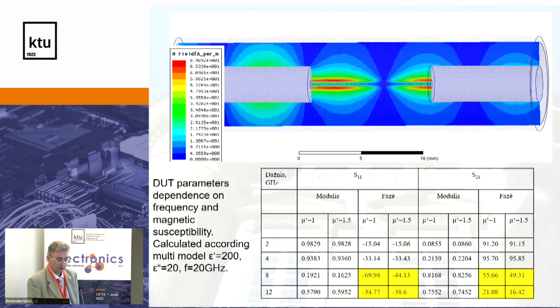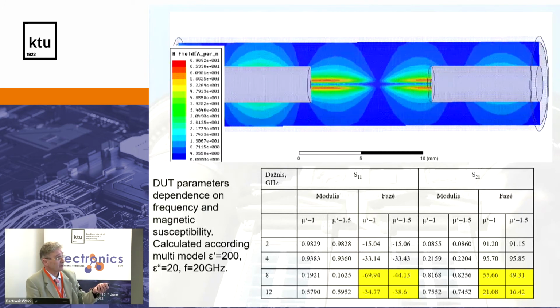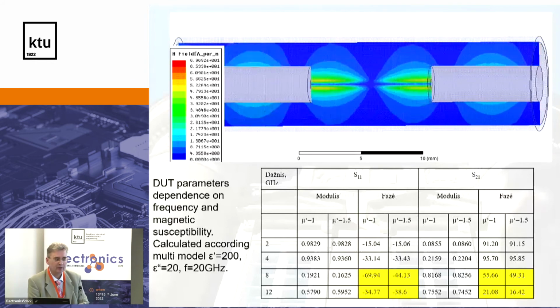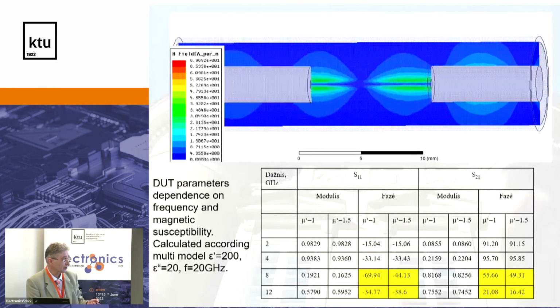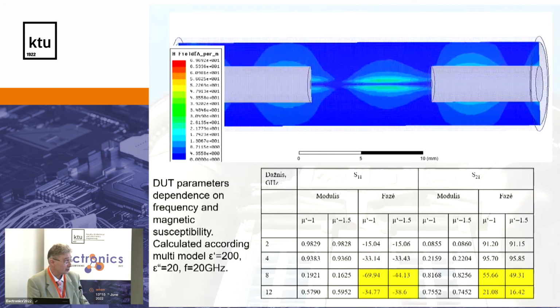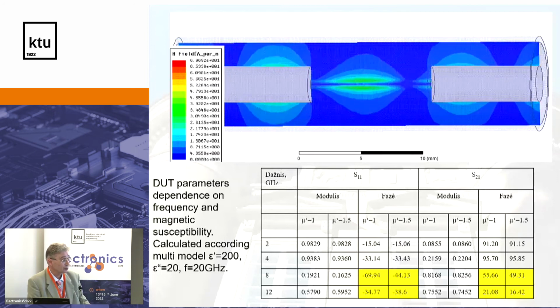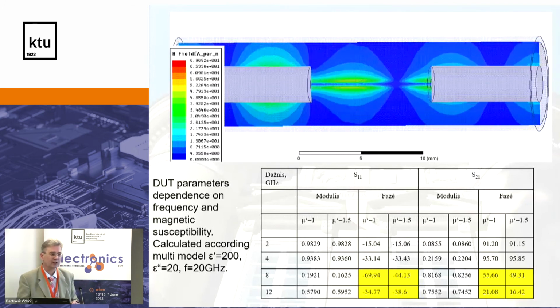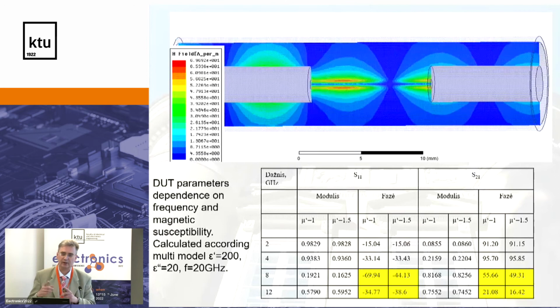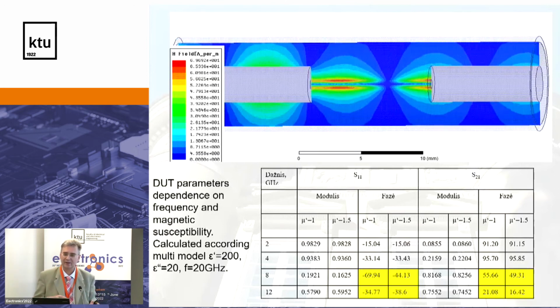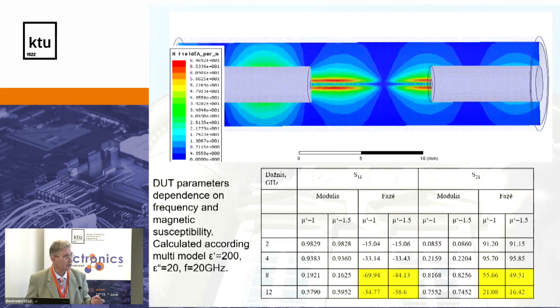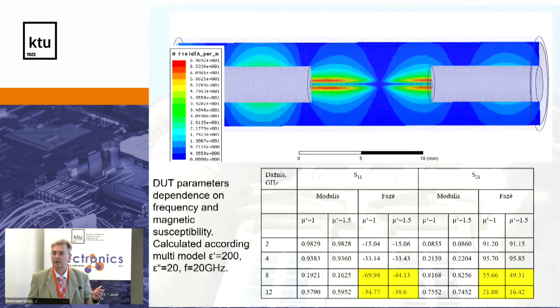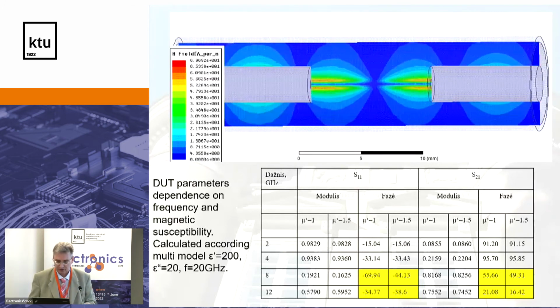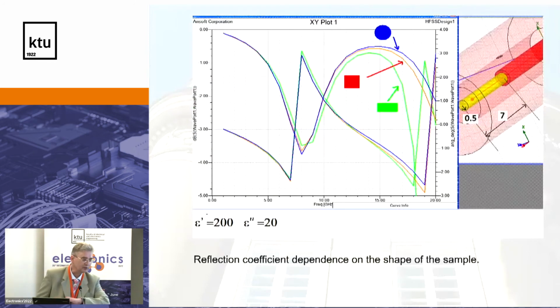And another interesting feature which I want to mention is that despite the fact that in the center there is the maximum of electric field and minimum of magnetic field, this method is sensitive to magnetic susceptibility. And you can see reflection phase changes due to magnetic susceptibility also. So you can extract, measuring simultaneously reflection and transmission, simultaneously magnetic and electric properties of the material. Even in this method, despite the fact that a better method, what I showed, was the ring method in the coaxial line. So how much time do I still have? 10 minutes. 10 minutes, okay, so I will speed up.